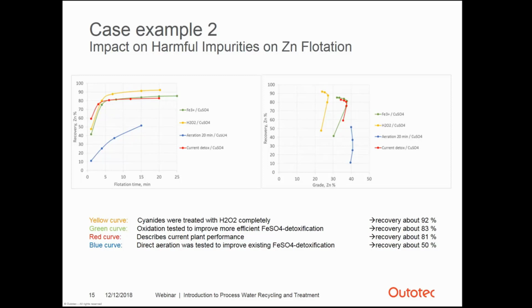The red curve in the recovery and grade graphs shows the flotation results with the current detoxification process, having a recovery of about 81% and a grade of 34%. The best zinc flotation results were achieved with complete cyanide destruction by strong oxidation with hydrogen peroxide, the curve presented in yellow. In the best zinc rougher flotation test, recovery was about 92% with a grade of 24% zinc. The required copper sulfate amount to float zinc was drastically reduced to 1/6 of its original amount after the process water was treated with hydrogen peroxide.